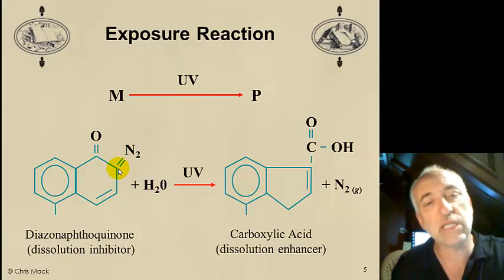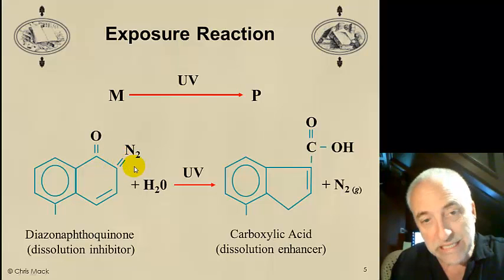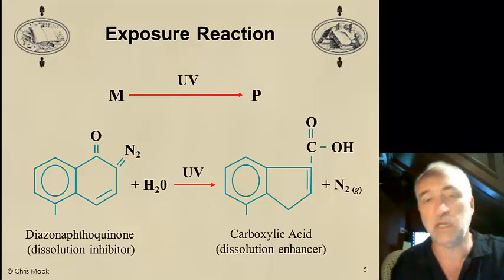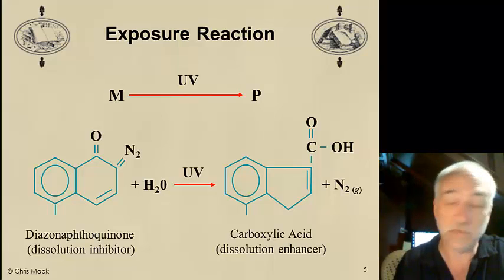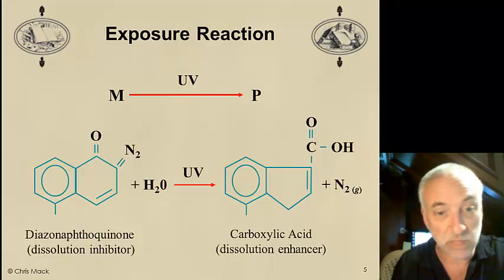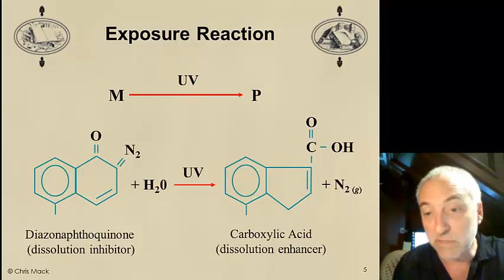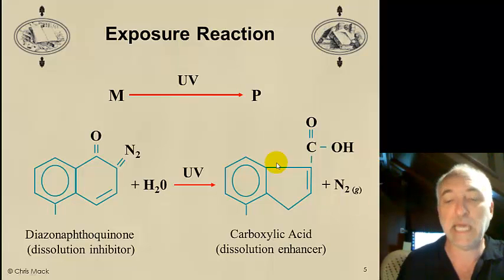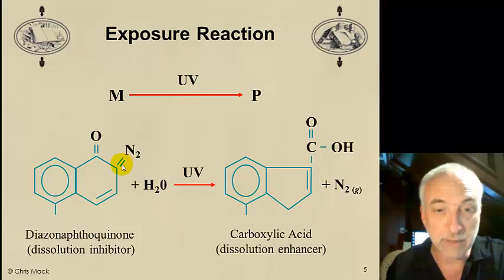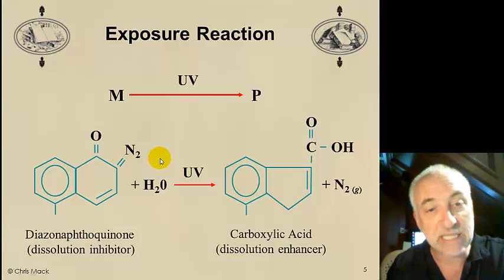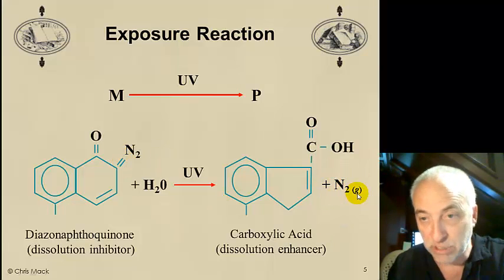Well, it's actually this double bonds of the nitrogen with the ring that is the light-sensitive material. Azo groups and diazo groups often make up dyes because they're sensitive to light in the visible region. And when we absorb light energy, here we break these bonds, and that's why the nitrogen gas comes off.